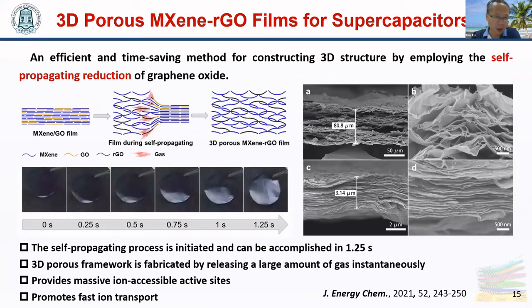graphene oxide. Firstly, we prepared the MXene graphene oxide film by vacuum filtration of the suspension of MXene and graphene oxide. When the MXene graphene film was slightly touched to the 300 degree heating plate, the self-propagating reduction of graphene oxide was initiated, and this process can be accomplished in a very short time, only 1.25 seconds.